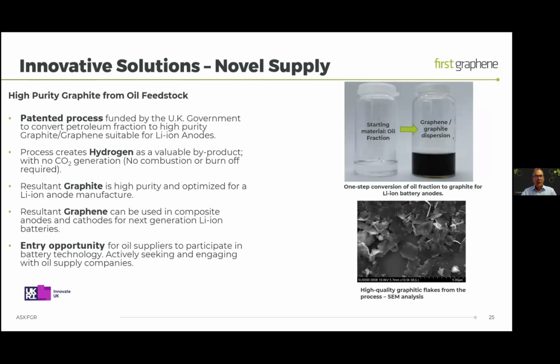The final slide today on the innovative solutions is something which is unique and disruptive. This is a technology that was developed by a UK-based inventor and is exclusively licensed to First Graphene. Essentially, it's a one-step process to convert oil fractions, so petroleum fractions, directly into graphite and graphene materials. The image at the top right of this slide, showing the water white vial being converted into a black dispersion, is exactly what happens. You start with a water white oil fraction, and running it through the process, it's a one-step process. You get immediate conversion into graphene and graphite materials.